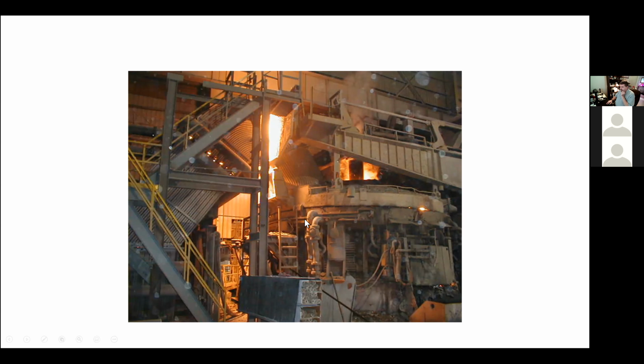So we're basically melting the steel scrap in here, once it's all liquid and we've finished removing silicon, phosphorus, and so forth, and it's hot enough and at the desired tap chemistry, then we're ready to tap the furnace. And what happens is that this whole structure tilts over.